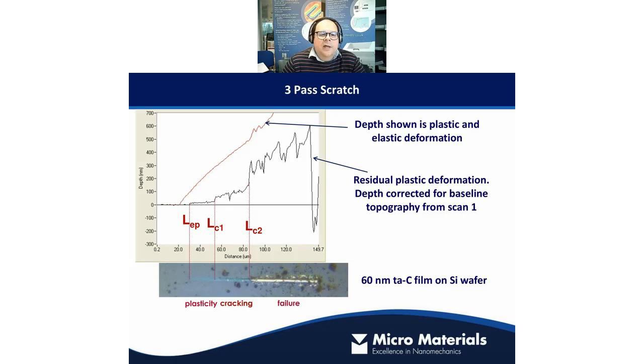So we can see now, when we've got all those various data sets together on one chart, we can pick out some events and we can match that up with our microscopy. We've got our big event here, which we saw during the loaded pass scratch, and we can see a corresponding big step in our post-scratch topography. That's basically complete film removal. So the sample is destroyed at this point. Basically, we've gone through the coating. We're now down to the silicon substrate.